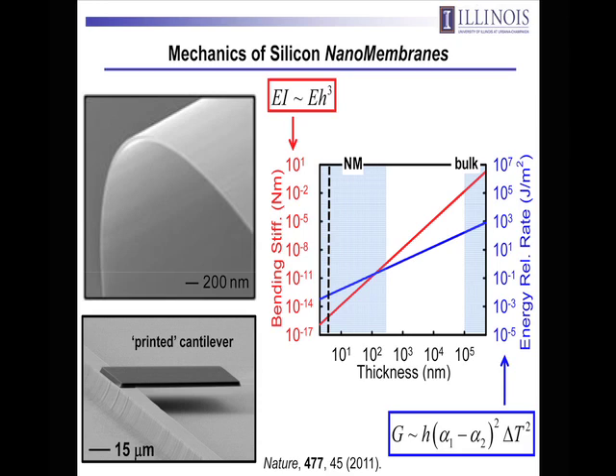The other consequence of thin is that for a given bend radius, the peak strains induced in the material are reducing linearly with thickness. And so as a result of making this thing thin, you can bend it to a very sharp radius of curvature without fracturing the silicon, which tends to fracture around a half or 1% tensile strain. So it's floppy, with very low bending stiffness. It's very bendable because of that linear dependence of the peak bending-induced strains on thickness.